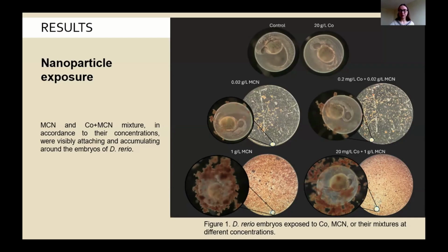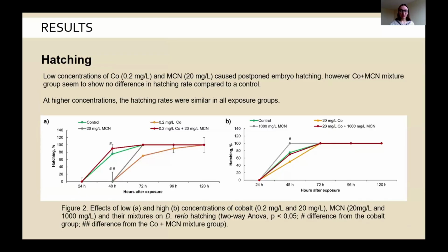Those concentrations were really considerable and were visibly noticeable by a microscope. And so what we checked was the hatching rate. Here on the left, you can see lower concentrations of cobalt, MCN, and their mixture. What we observed is that lower concentrations of cobalt and MCN caused postponed embryo hatching. However, the cobalt plus MCN mixture group seemed to show no difference in hatching rate compared to the control group. And this could suggest that the mixture has lower toxicity than cobalt or MCN separately.